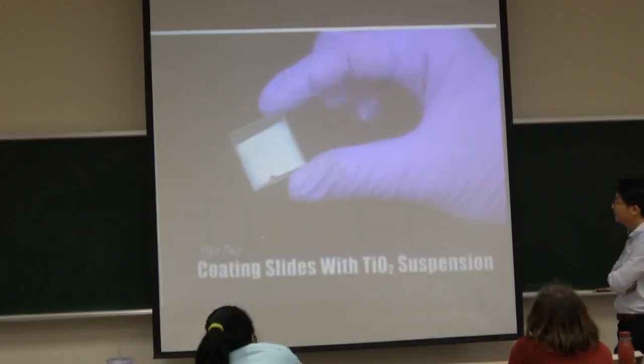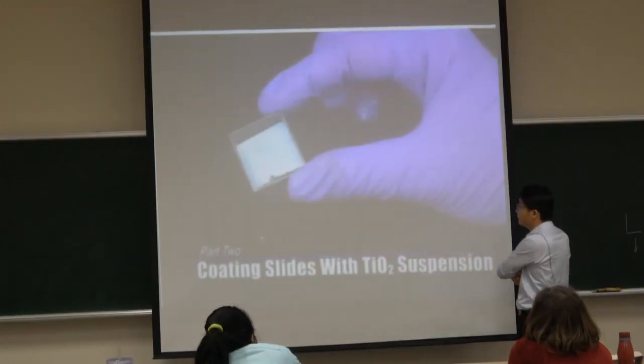Part 2. Coating slides with the titanium dioxide suspension. Step 1. Clean 2 conductive glass slides by rinsing them with a wash bottle filled with ethanol. Gently dry them with a soft tissue. Step 2. Use a multimeter set to resistance, ohms, to check which side of the glass slide is conductive. The slide should conduct between 10 and 30 ohms on the conductive side and nothing on the non-conductive side. There should be a slight visible difference between the conductive and non-conductive sides as well. The conductive side will appear bluish and cloudy, while the non-conductive side will appear clear and yellowish.